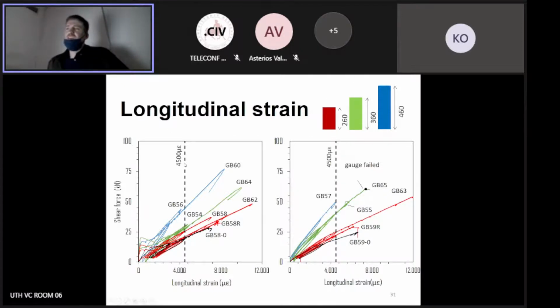So you see that I said before that up to 0.45% or 4,500 microstrains, if you will, actually nothing should happen to the beams. But the tallest beams, which are not really that frequently tested in the labs, actually showed me that you can get a little bit below that 4,500. And if you test even larger, what I found out later, you can get even lower strains. So actually, that gave me already an indication that there is something not consistent with the current state of the art at that time I was studying.